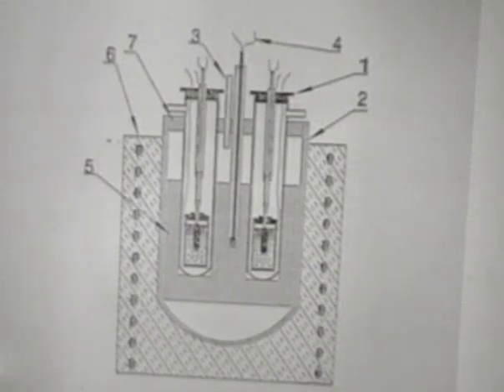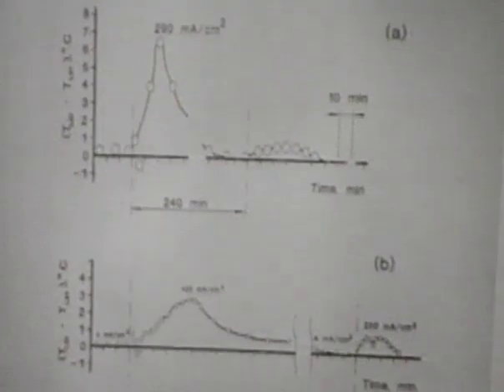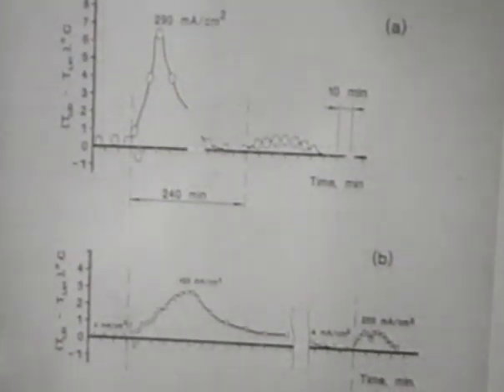Temperature difference across the oven was no worse than 0.5 centigrade, so the conditions were very similar. Again, the experiments were exactly like Dr. Liao made, and he ran about a 1.5 day loading cycle with low current, about 4 milliamps per square centimeter in the anode, and then applied a sharp current increase.